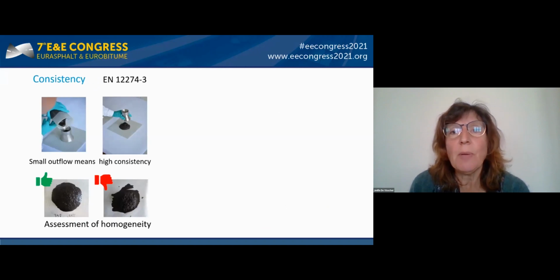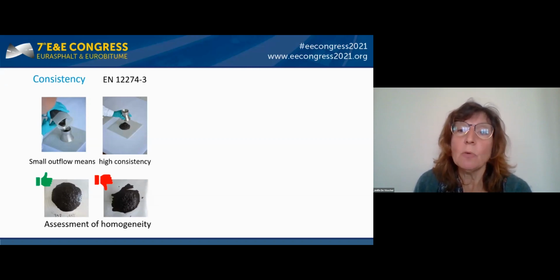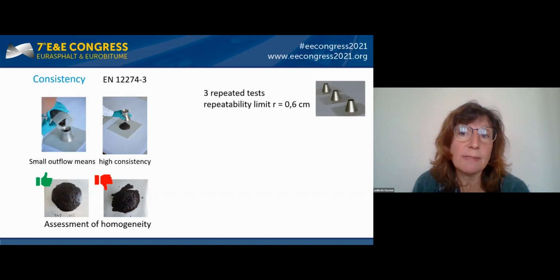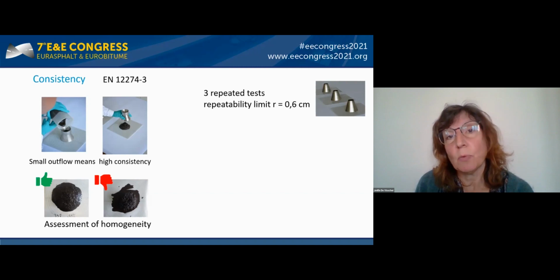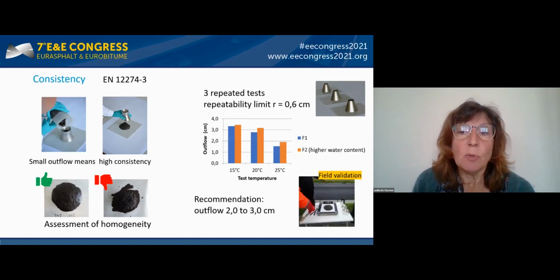So for consistency, we have the European test methods where the fresh mixture is poured in a cone and the radial outflow is measured after the cone is lifted. At the same time, the operator can assess the homogeneity. And here we found that 3 repeated tests are necessary. And after optimizing the test procedure, we obtained a repeatability of 0.6 centimeters. And in this way, we can logically discriminate mixtures with different compositions. As an example, here we see how the outflow decreases at higher temperature and increases when more water is added to the mix.